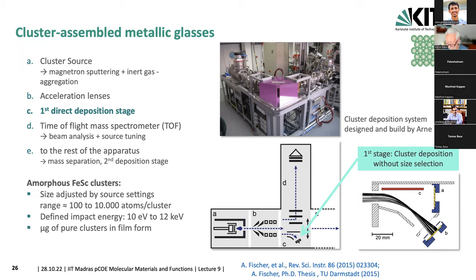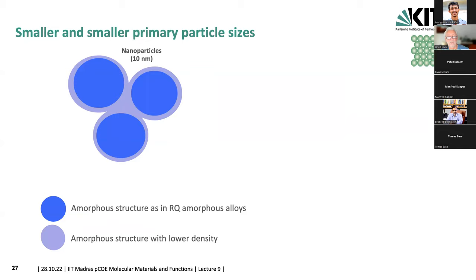And this is kind of what we are trying to do. This is what is done by compaction. You start with particles, let's say 10 nanometer, and you consolidate them and you put a high hydrostatic pressure on them, and you form this lighter blue interfacial region, which is structurally different, but still amorphous. And it's also responsible, for example, for changed magnetic properties.